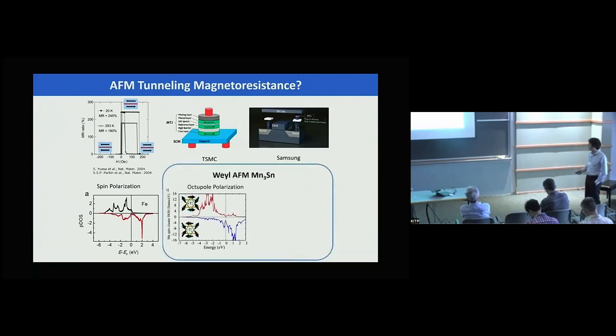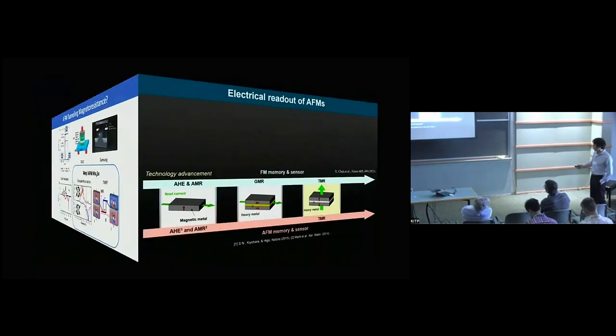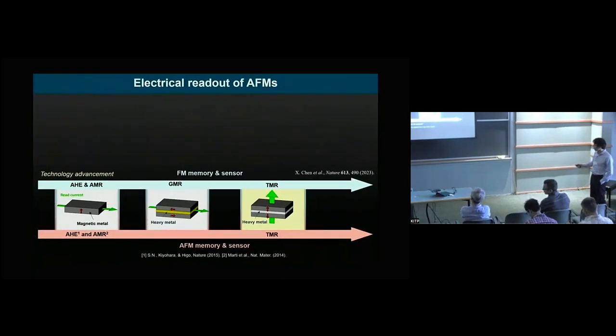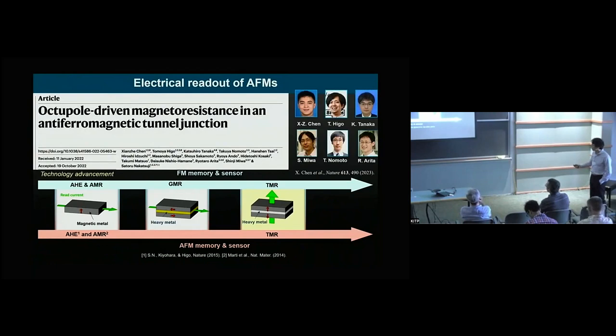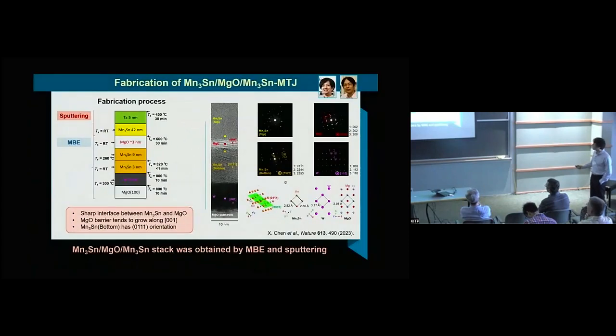But this material breaks time reversal, and in particular, the octopole polarization forms the polarization of the ferroic order. So we wanted to see whether it allows us to see a tunneling magnetoresistance. This is a kind of R&D roadmap: anisotropic magnetic resistance, GMR, TMR, and see whether this is possible for antiferromagnetic systems. And this is exactly what we recently found for the octopole system. So I want to tell you a little bit about the detail.